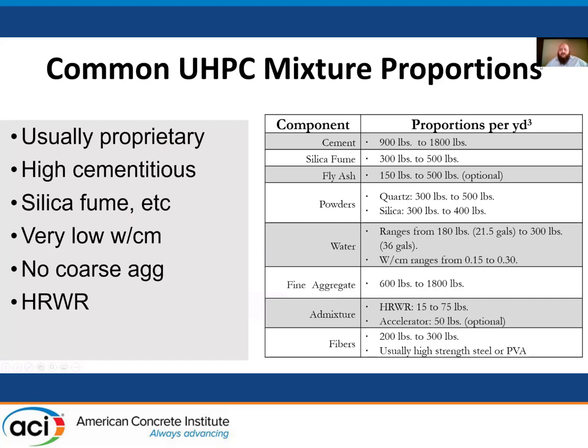There are a few things I may have missed, because you can only put so much in a table at once. But typically what you're going to find is quite a bit of cementitious material, whether that's cement. You're going to find usually some silica fume or metakaolin. A lot of times to make it more economical or more durable, you're going to provide a little bit more fly ash. And you don't see any coarse aggregate here, but you see a lot of fine aggregate. And then you're going to see a high range water reducer at a pretty high dosage rate.